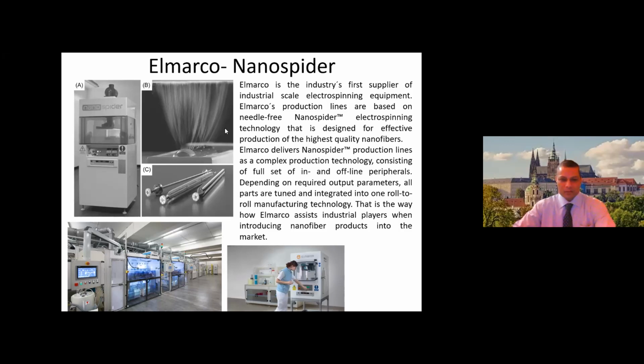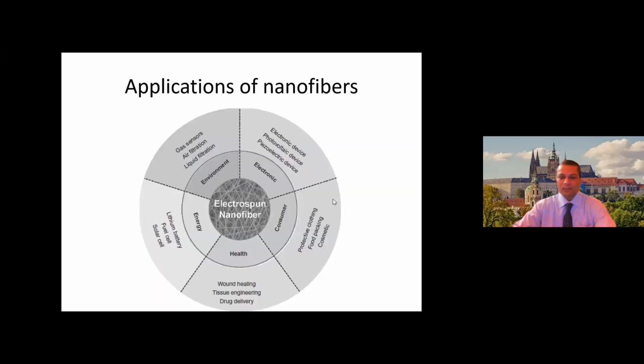And we must be thankful to these and other companies around the world who have produced and supplied several tons of nanofibrous membrane in the pandemic era, because we know that the masks that are used, especially N95 masks and FFP2 masks, all have multiple layers of textiles or nanowovens especially, and the middle layer, or the functional layer, is definitely a nanofibrous layer. And this nanofibrous layer has porosity in the range of very fine dimensions, especially nano dimensions, so that it doesn't allow the droplets containing the virus to pass through. And if we are in an infected environment where the virus is moving around in the atmosphere, it doesn't pass through the mask, and we are protected.